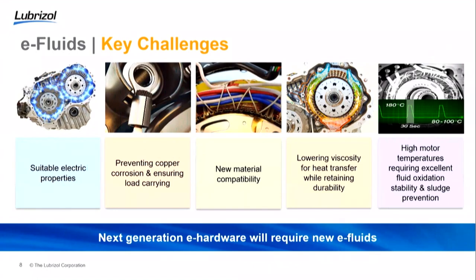If conductivity is too high, then you may risk shock, for example. But if it's too low, you could have static buildup. So really, you want the optimum electrical properties for the device. Very important is protecting copper parts from corrosion. A lot of the chemistries used in load carrying, the salt chemistry that protects the parts, can harm copper. So again, it's about balancing those performance characteristics.